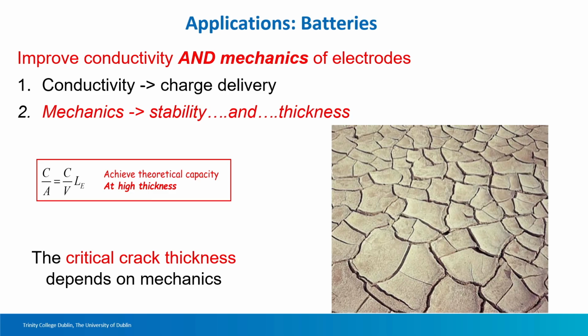The thing is, the bottleneck of the industry is that you can only go up to a certain thickness of your electrodes, above which you reach what we call the critical crack thickness. Effectively, the electrodes are not freestanding anymore. And this becomes a huge problem, and this is why lithium-ion batteries reach the limit that we all face. So what we